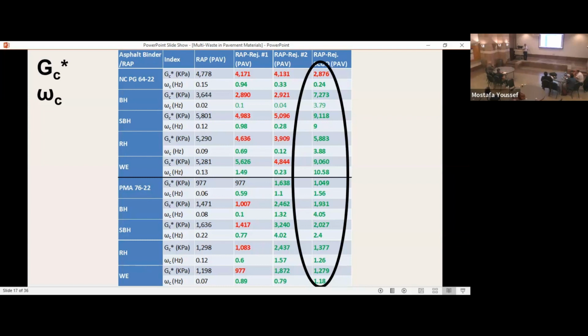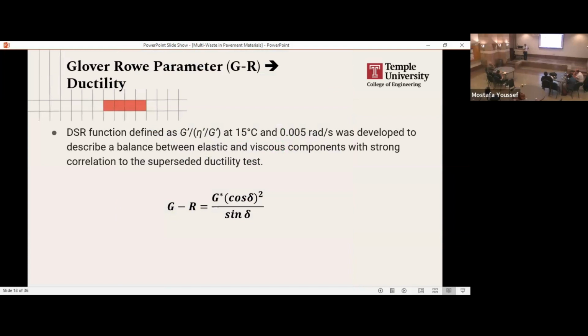How does that translate to actual performance? So we conducted mixture level testing, as I will show you later. But we also wanted to look at what the state of the art is, of what is being applied in the asphalt industry right now. Right now, everybody's going after this function because it is a measure of asphalt ductility. It's called the Glover-Rowe parameter. It is measured from the master curve at a specific frequency and a specific reference temperature. And it's highly correlated to the ductility of the asphalt through other tests and field studies. So a lot of DOTs are trying to push for using this parameter to replace the typical Superpave parameters for fatigue cracking.